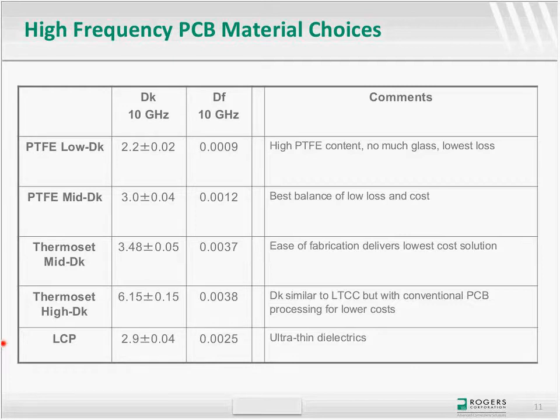But for these materials that I've listed in this table, if you go to high enough frequencies, you will find that mainly for low loss tangent materials at high frequencies and thin dielectrics, conductor losses could be 75–80% of your overall insertion loss over the dielectric.